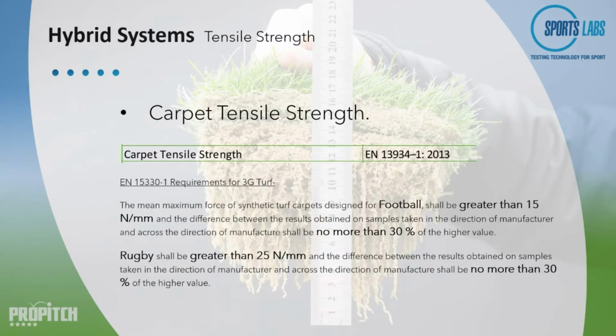Again, currently there are no requirements for hybrids, but we can compare these with the requirements for 3G systems. The EN 15330 standard requires a minimum value for carpet tensile strength of 15 newtons per millimetre and less than 30% difference between the two directions. Rugby require a minimum of 25 newtons per millimetre, also with less than 30% difference between the directions of manufacture. We have seen hybrid systems that can meet these requirements.